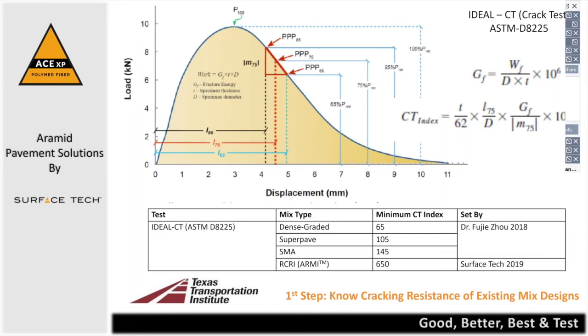Yeah, so as we look at this, the original document and some of the guidelines that were presented were for mixes down in Texas. For the dense grade down there, he was suggesting a minimum CT index of 65. A Superpave mix, which might have more liquid and more crushed stone in it, a 105. Then you're getting to an SMA, a stone matrix asphalt, that has quite a bit more liquid in it, and so from a cracking perspective should do extremely better. There's a 145, and you'll see I've added our ARMI line there, our asphalt reinforced mixed interlayer product, and you're seeing a minimum ideal CT index of 650. Keep that in mind as we move forward.